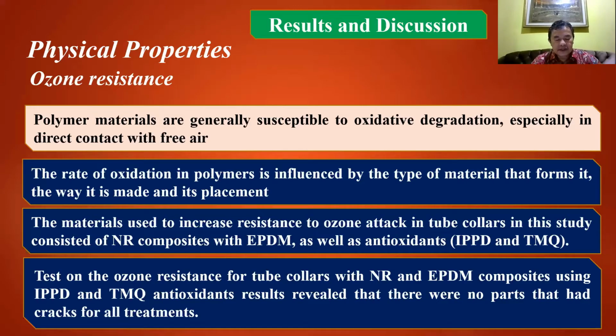Physical properties also include resistance. Polymer materials are generally susceptible to oxidative degradation, especially from direct contact with air. The rate of oxidation in polymer is influenced by the type of material, the weight, and its filler. Compression sheet EPDM as well as antioxidant IPPD and TMQ. Test on the ozone resistance of composite with NR and EPDM compression sheet using IPPD and TMQ antioxidant. The result was that there were no cracks for all treatments.